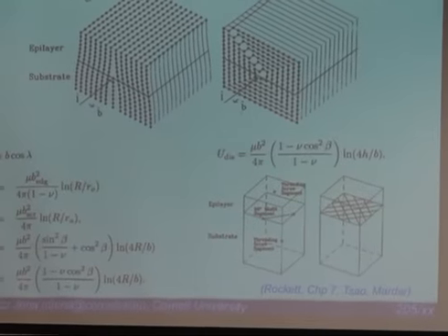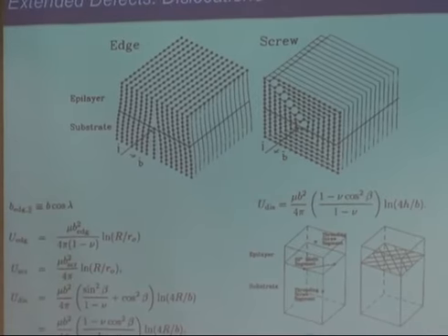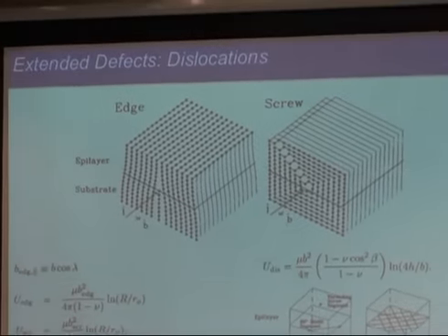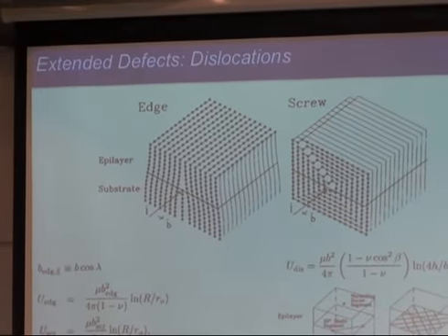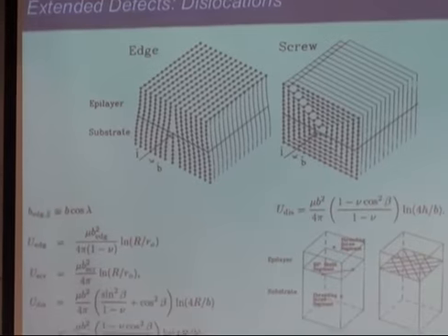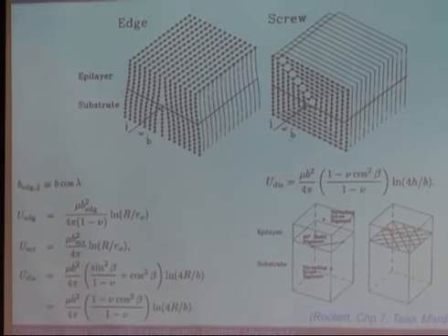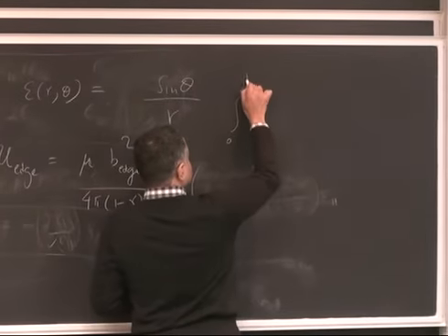And physically, obviously there's no 0 in a physical dislocation, right? The strain is not infinite, it's finite in all places. So the way you cut it off is essentially the lower limit of the integral takes care of two things. So when you integrate, instead of integrating from 0 to infinity, you can say big R.